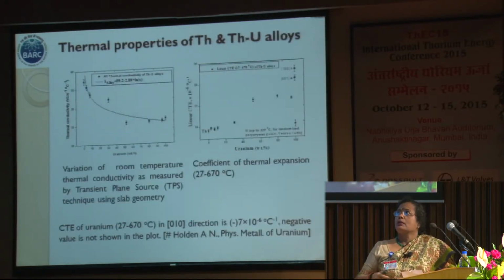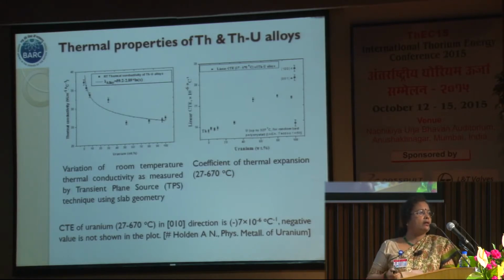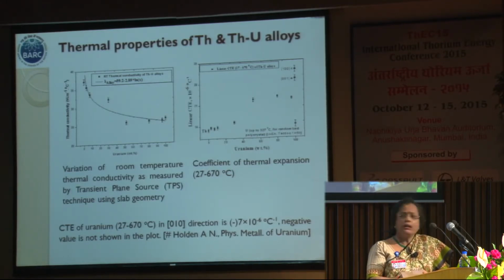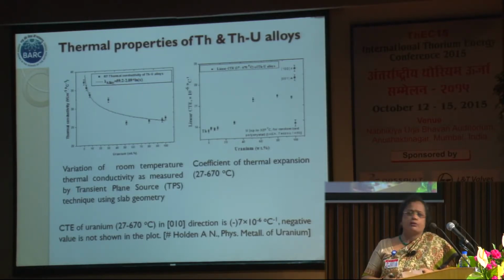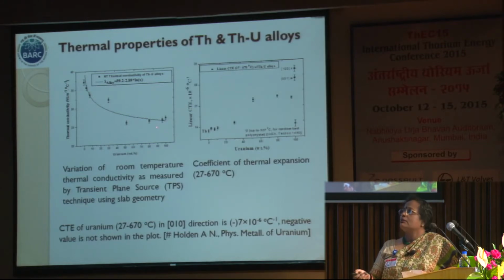So this condition is a very useful condition for this fuel. We also wanted to see other properties like thermal conductivity and the coefficient of expansion. Here we could see that at room temperature, when the uranium concentration is increased, as expected the thermal conductivity decreases, but in the range of 3 uranium percent it is still much higher. Similarly, for the thermal expansion coefficient, till 15% of uranium there is not much thermal expansion. Beyond that, it increases.